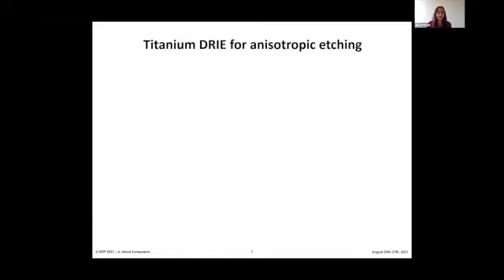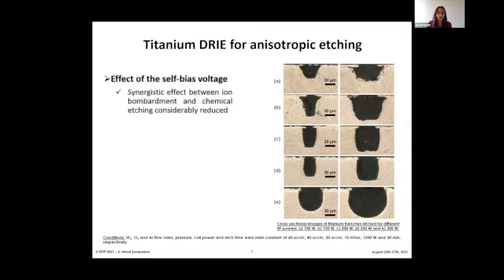Lateral etching can be reduced either by adjusting the oxygen flow rate or by tuning the self-bias voltage. To investigate the influence of voltage, 2 independent studies were conducted. The first one on the RF power, i.e. the RF power source connected to the cathode that generates DC bias and attracts ions to the wafer. And the second one is pressure.